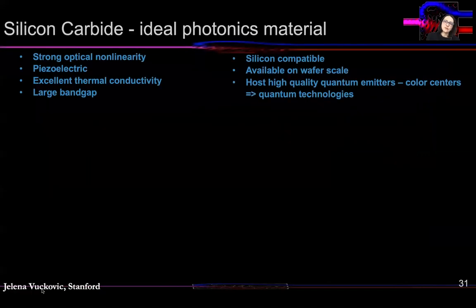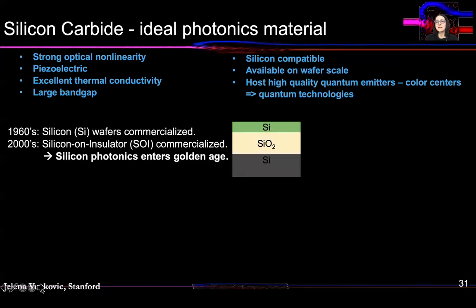The other material that we are actively working on is silicon carbide. Silicon carbide is a very interesting material for quantum photonics because of the color centers and the ability to make good high quality photonics. But it's also a very interesting photonics material because of the strong optical nonlinearity, being piezoelectric, good thermal conductivity, silicon compatibility, availability of wafer scale, and a large band gap.